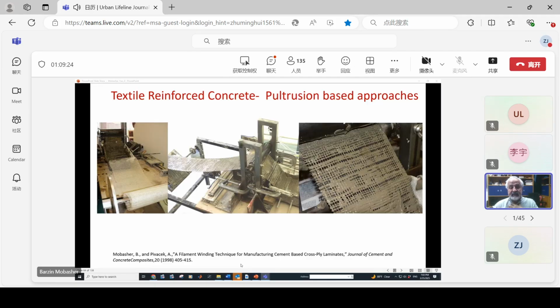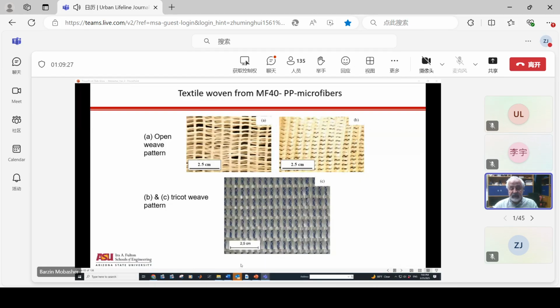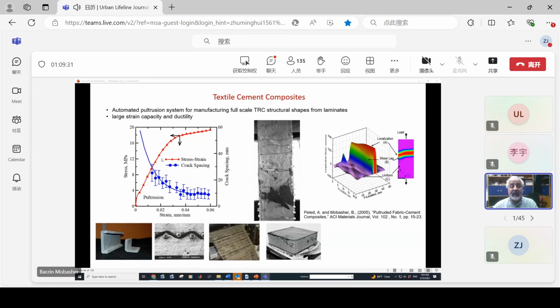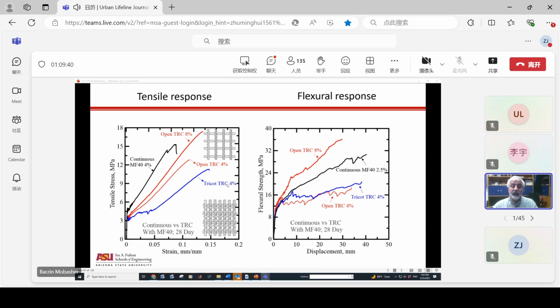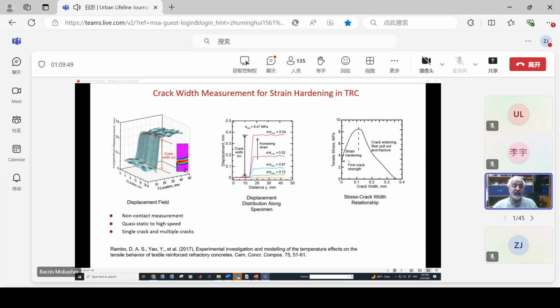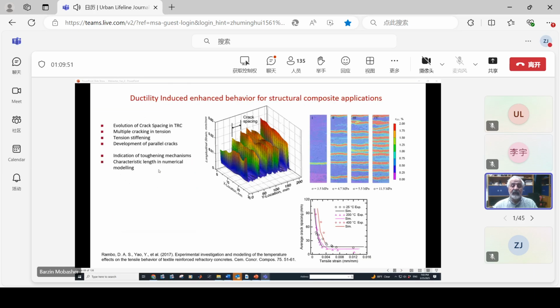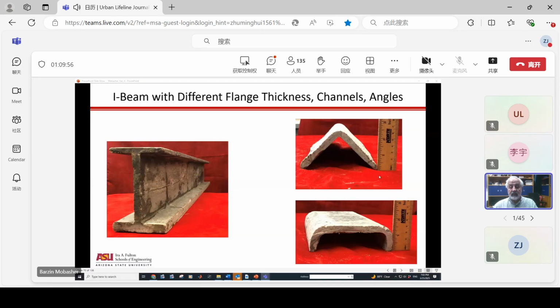Textile Reinforced Concrete is another area that we have published significantly with Dr. Yao, and that shows that we're using the same mechanisms to do distributed cracking and monitor the crack width and the crack spacing for different types of systems. So here, the TRC actually allows me to design it in tension with 15 megapascals. And we have measured the crack width and how we can generate the distributed cracking in our systems.